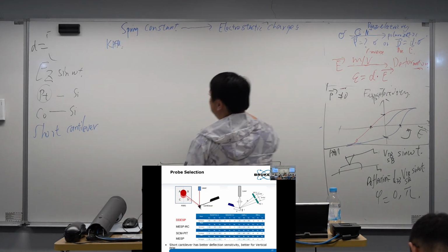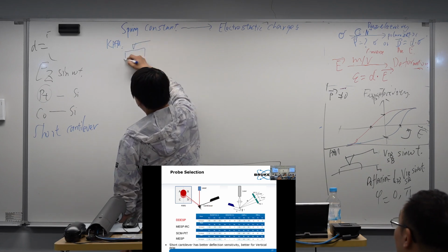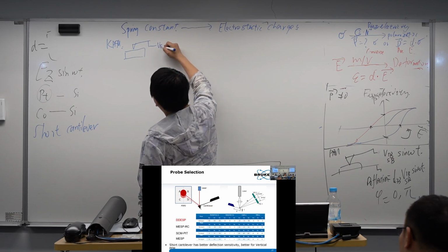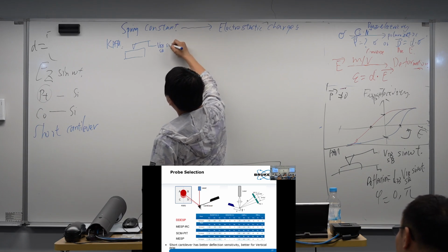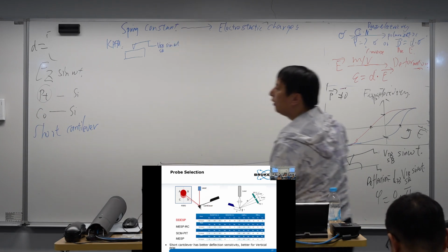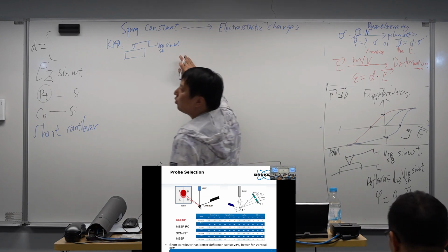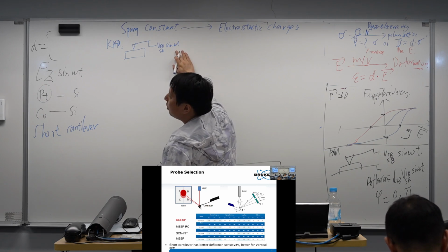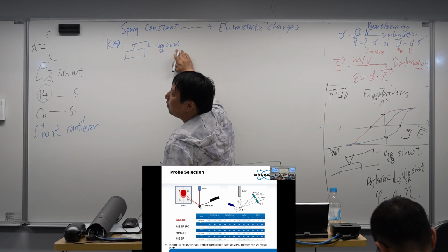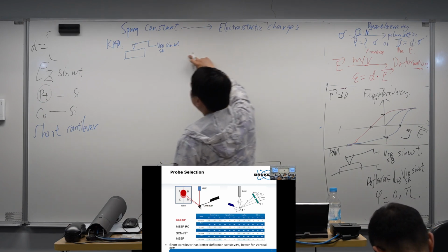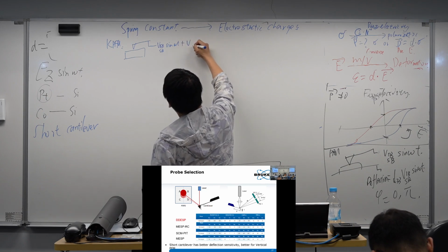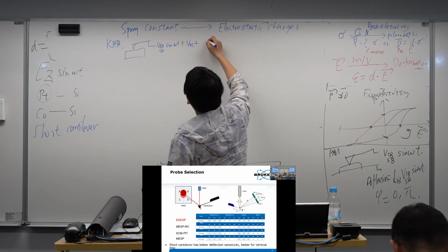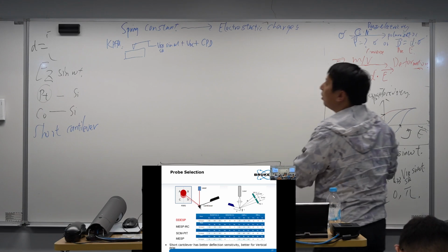And what's the KPFM? It's the probe. It's the sample. We apply certain sample values or tip values on the probes, sine omega t, right? And this omega could be anything, but for usual setup, we choose this omega to be omega 0, okay? After we apply these things, we can apply a VDC, and there will be a sample tip potential difference, right?